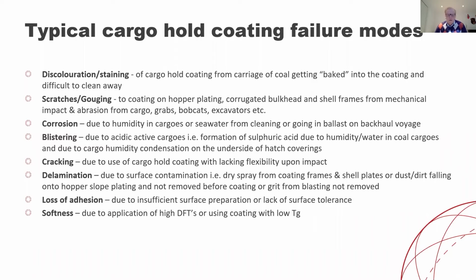You have scratches and gouges to the coating, which come from impact and abrasion from cargoes that you are carrying, but also when you are loading and offloading from grabs, bobcats, excavators, etc. Corrosion, of course, is a big issue due to humidity in cargoes or seawater from cleaning or going on ballast, as I already mentioned. Blistering: acidic active cargoes could create blistering in your coating.